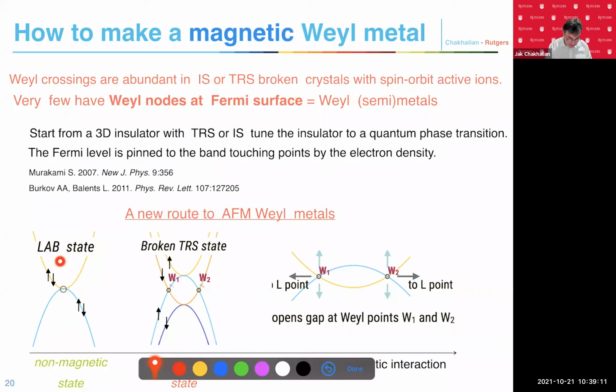So to answer a very good question, with a lot of insight in there: if you start with this unusual phase in the pyrochlore, you always end up with the Weyl phase once this specific antiferromagnet sets in. But it also requires the spin-orbit coupling, because the band structure is specific to generate this. Plus, it needs very moderate magnetism. Otherwise, you just push them to the edge of the Brillouin zone. That's the reason a lot of antiferromagnets are just trivial Mott insulators, correlated magnets, non-topological.